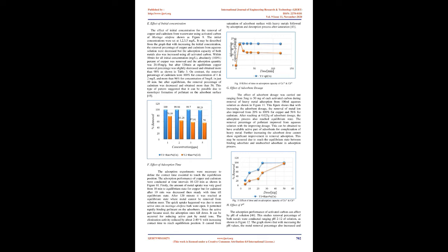See Langmuir and Freundlich isotherms. The Langmuir isotherm expresses a monolayer of the metal ions on the adsorbent. The experimental Qmax for Moringa oleifera was found to be 20.43 and 17.01 for Cu and Cd, comparable with the theoretically calculated Qmax as given in Table 1. The higher value of b describes the affinity of the adsorbent to adsorb metal ions. The value of Qmax can also be considered as the total number of active sites of the adsorbent. According to Table 1, the affinity order of Moringa oleifera is Cu > Cd.